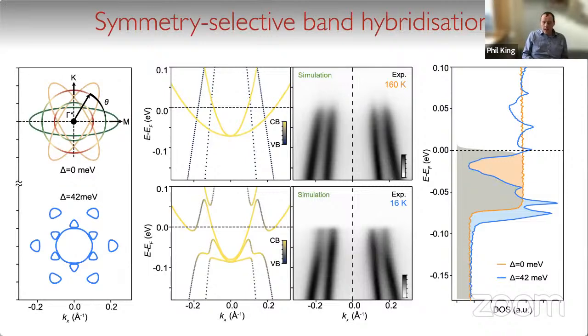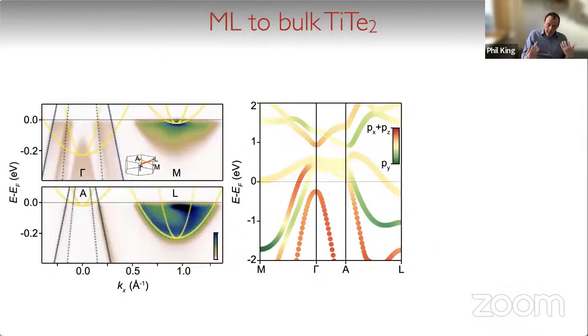Okay, so how does all of this compare or relate to the story of band inversions that I was talking about in the first part of the talk? Well, it turns out that if we now look at the case of bulk titanium ditelluride, you can see, it's a bit in a pale shading here, but you can see as a function of the out of plane momentum in this system, we have just the same sort of kz dependent band inversion as we had also in the palladium telluride and the other transition metal dichalcogenides. And one of the things that does is it effectively inverts the ordering of the px and the py dominated states for the inner and outer valence bands in the gamma plane of the system and in the A plane of the system.